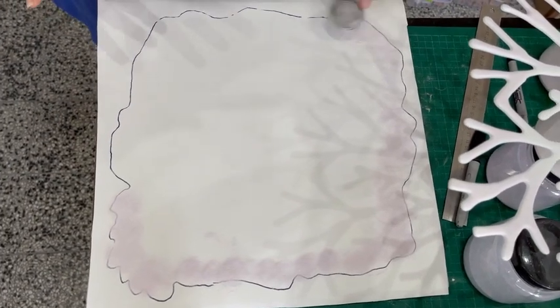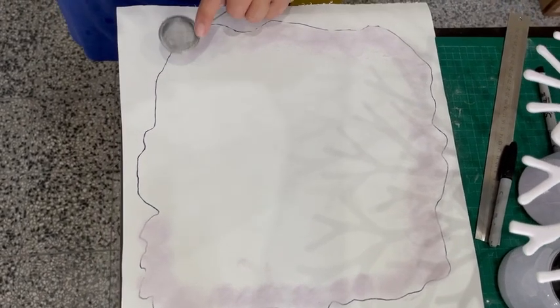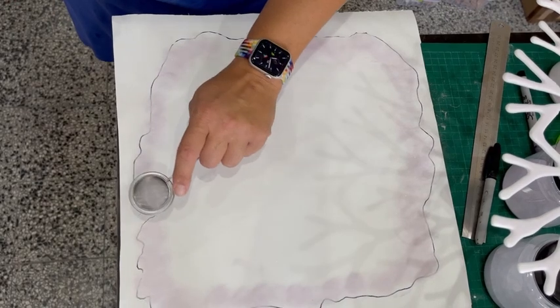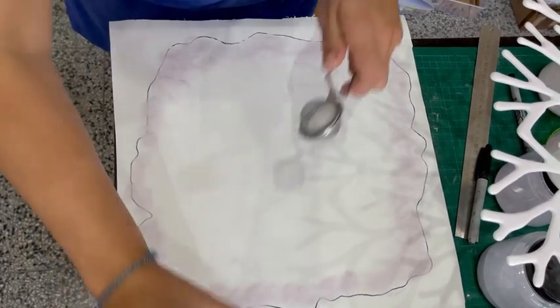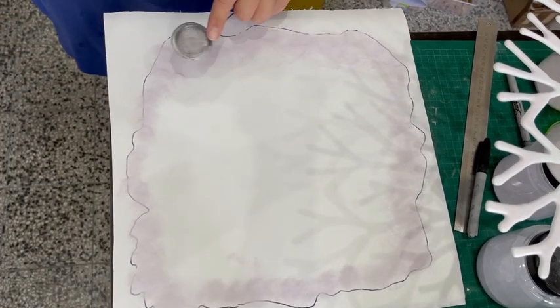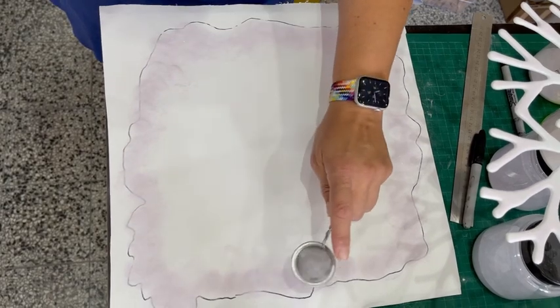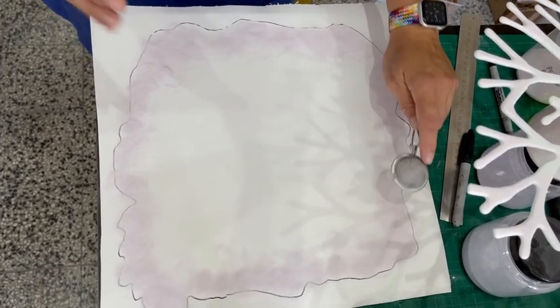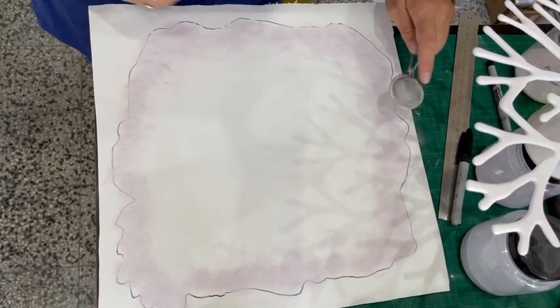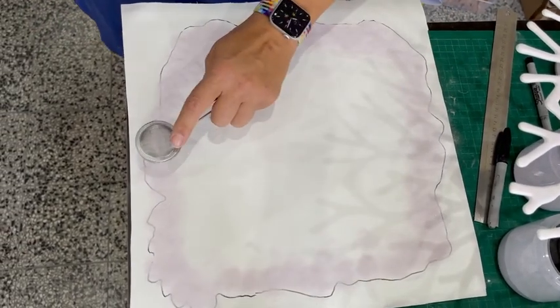If I had fired it the other way around, this powder would have slid off the convex side, and you still would have had white and also the devitrified glass poking through. Whereas this way, flipping it over, I've got the flat side of glass to lay the powders on, and then the round side will sit into these powders. And yes, I'm going to lose a little bit between the voids, but it shouldn't be too bad.